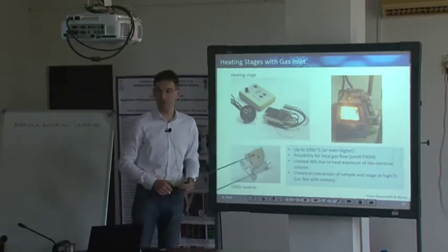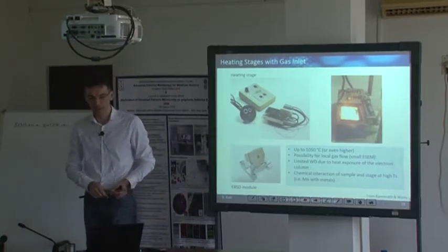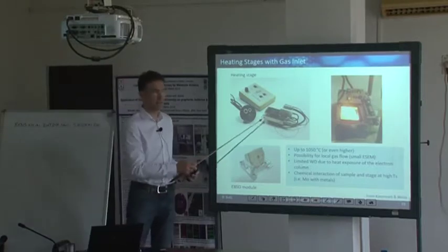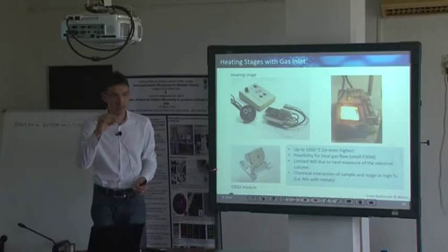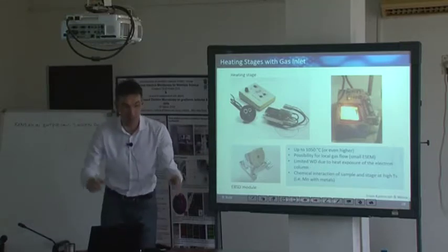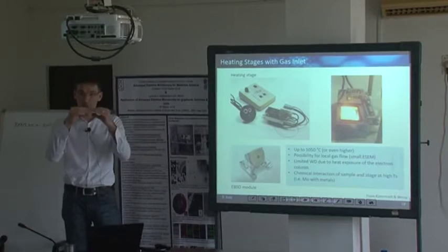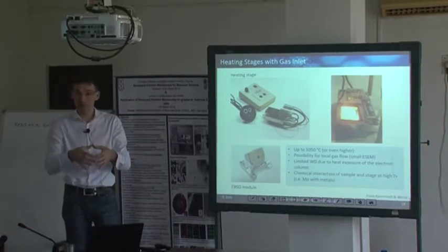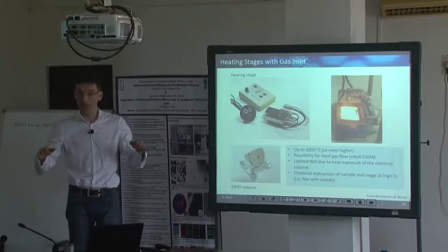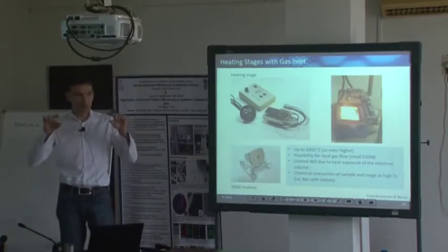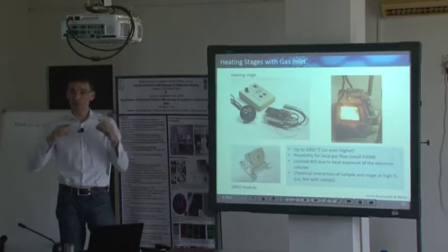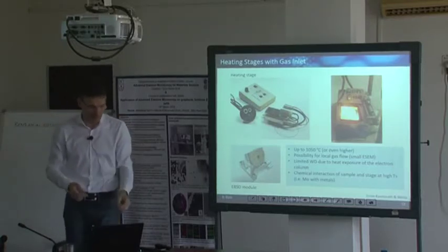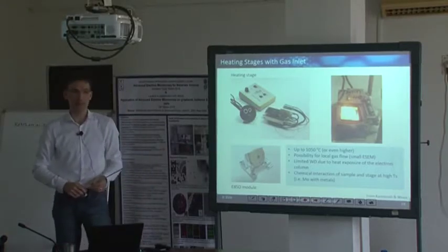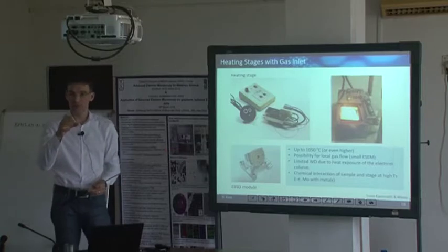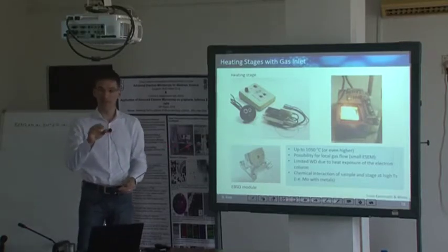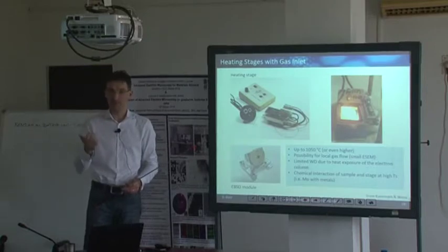And it turned out, in just a few recent publications in the field, that in environmental TEM, for instance, if you have a very thin TEM sample, you can easily imagine that if you heat from the outside, the heat has to be transported to your innermost region. But in the innermost region, you have a huge surface available to lose energy, and a very limited cross-sectional area available to transport and add energy. So during environmental TEM measurements, the temperature of your region of interest might be off by a few hundred Kelvin from the preset temperature of your heater.